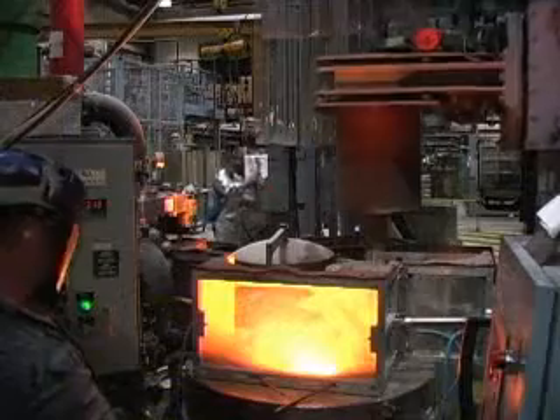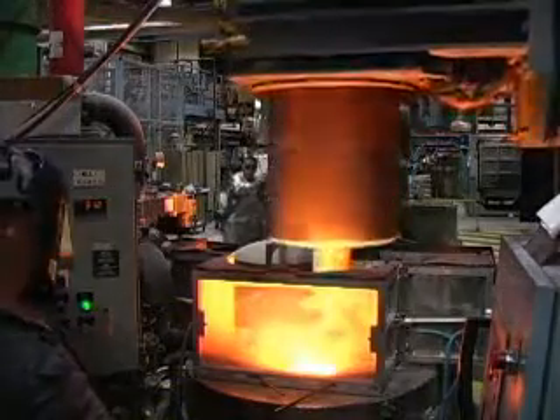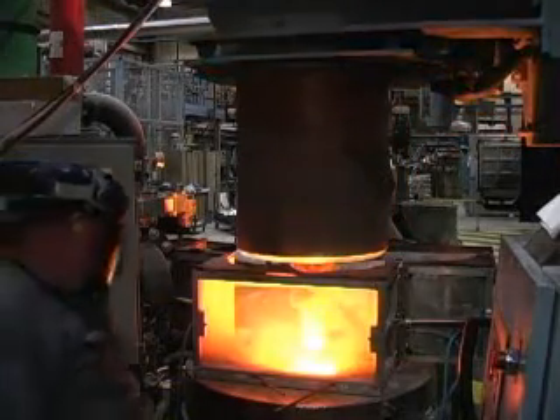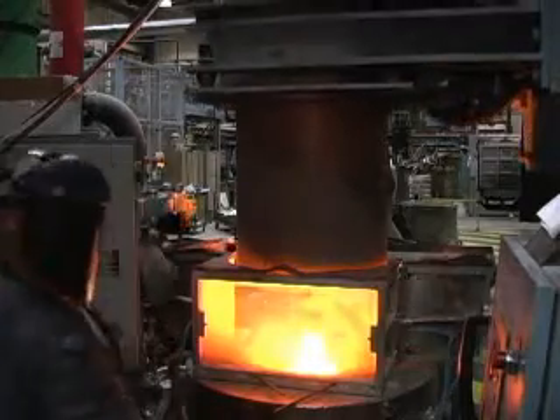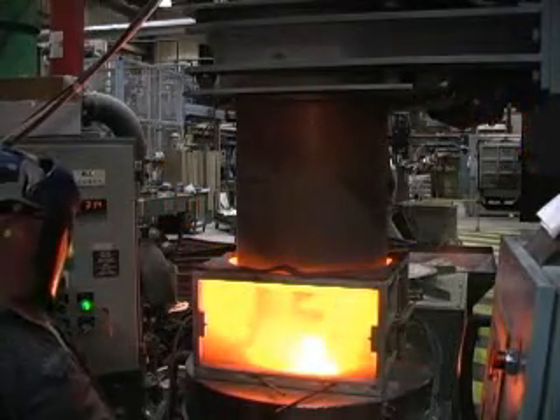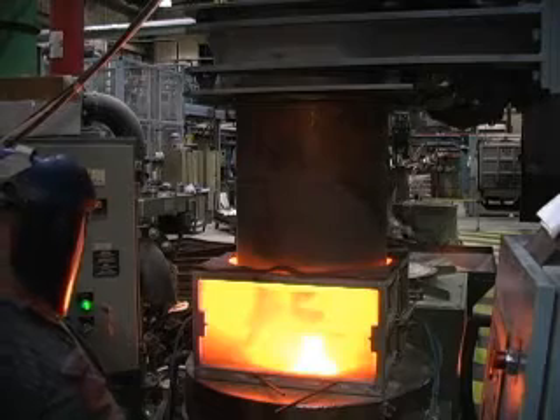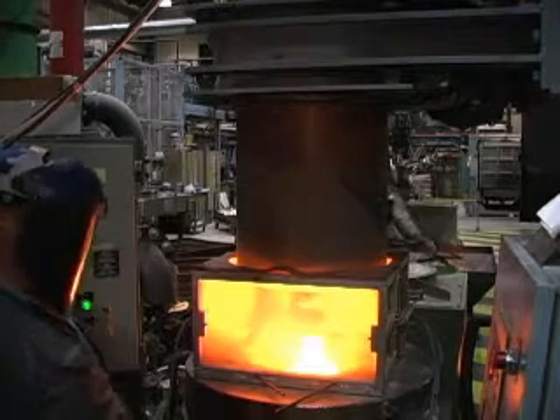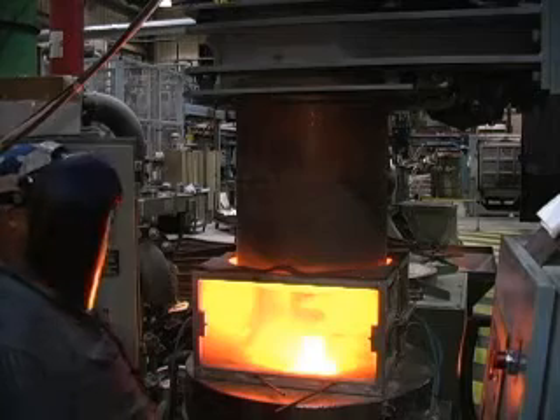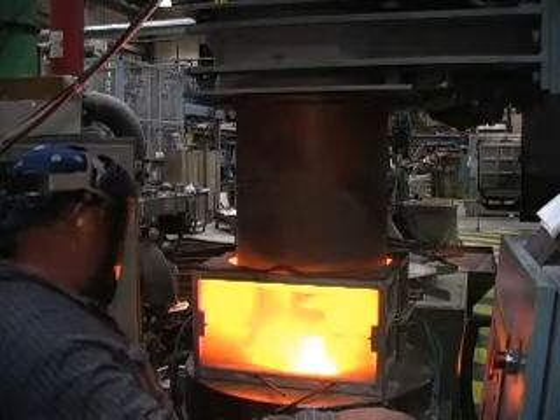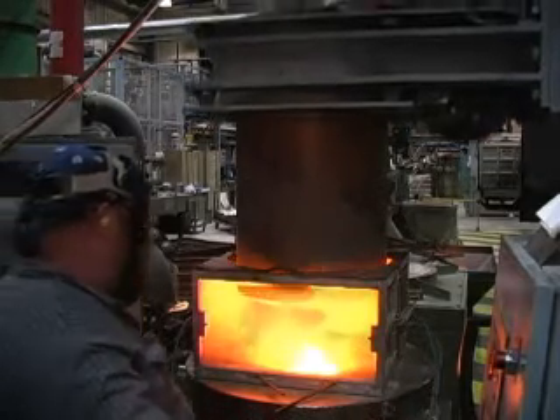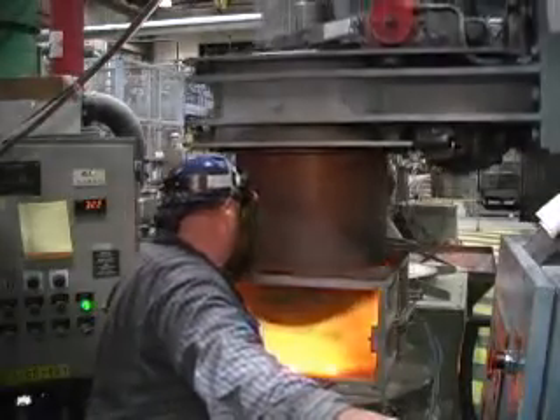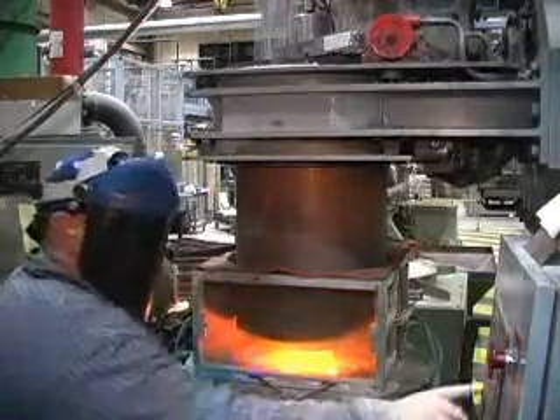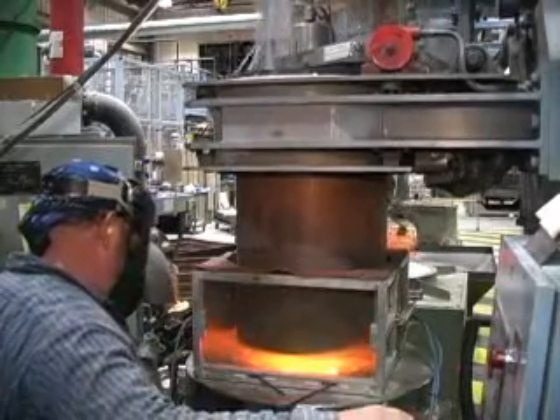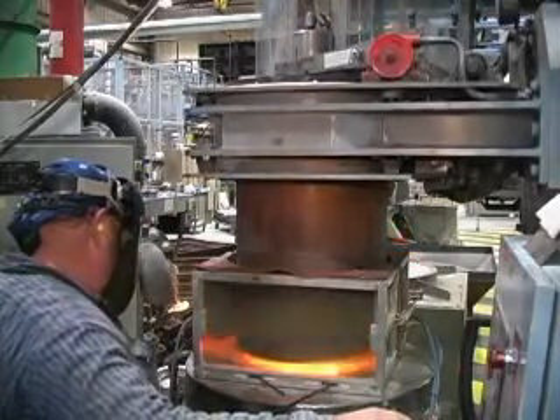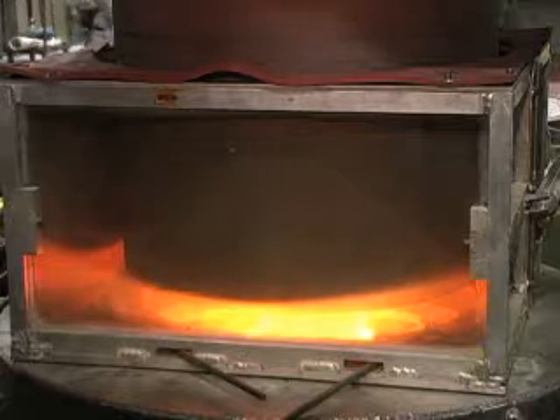For this application, a CLI casting unit which blankets the molten metal with an inert gas is being used. The fill pipe is first lowered into the inert atmosphere. A partial vacuum is momentarily applied to the chamber, eliminating air within the mold and replacing it with inert gas. The chamber is further lowered until the snout is submerged a precise distance into the melt. When the chamber is again partially evacuated, the inert gas, which blankets the melt at atmospheric pressure, causes metal to flow upward into the mold, completely filling the part cavities.